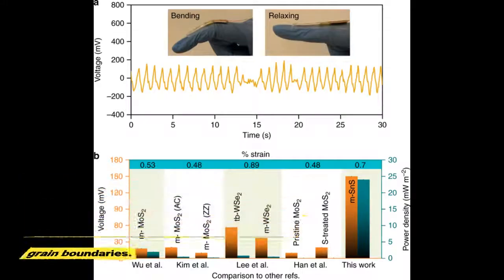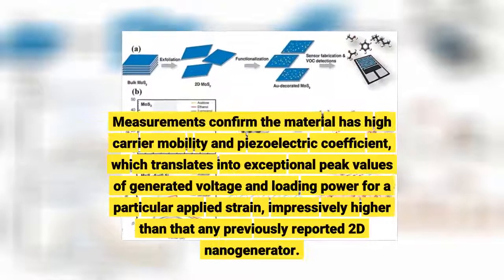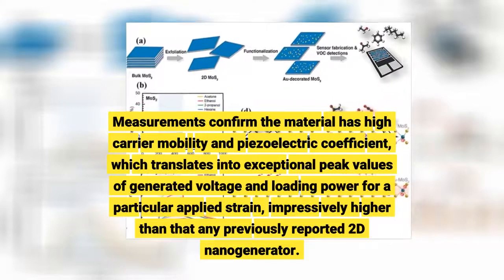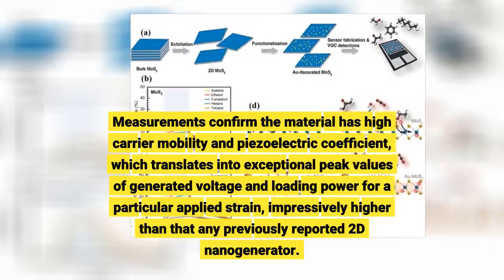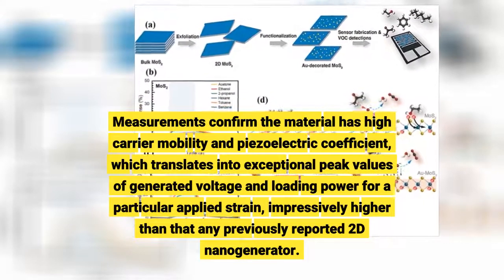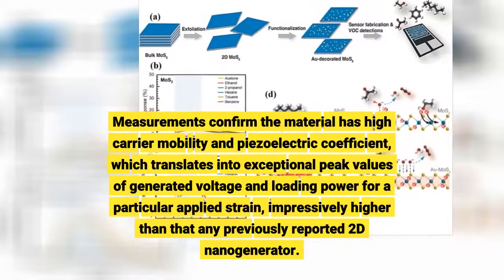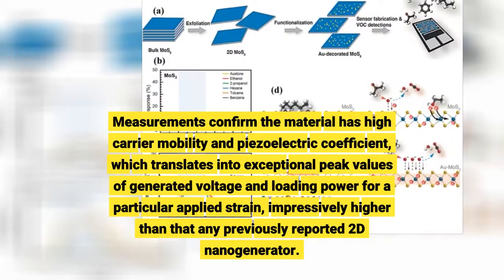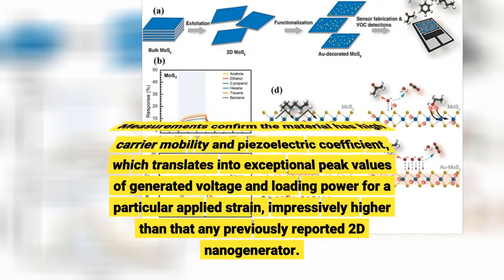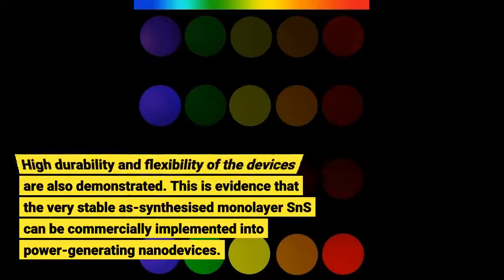This liquid metal-based method allows us to extract homogeneous and large-scale monolayers of SnS with minimal grain boundaries. Measurements confirm the material has high carrier mobility and piezoelectric coefficient, which translates into exceptional peak values of generated voltage and loading power for a particular applied strain, impressively higher than any previously reported 2D nanogenerator. High durability and flexibility of the devices are also demonstrated.